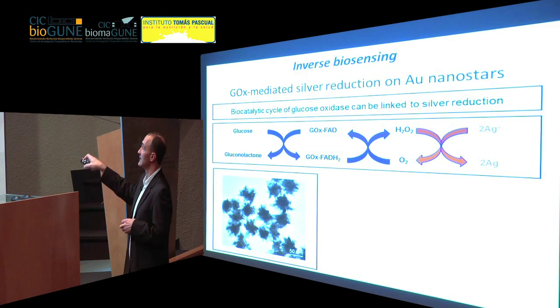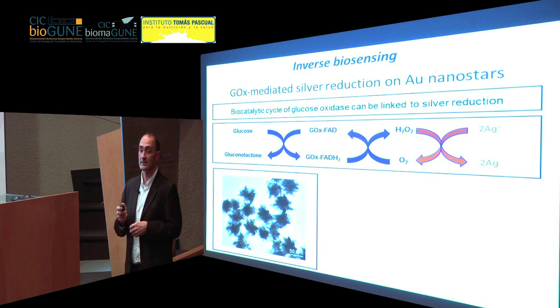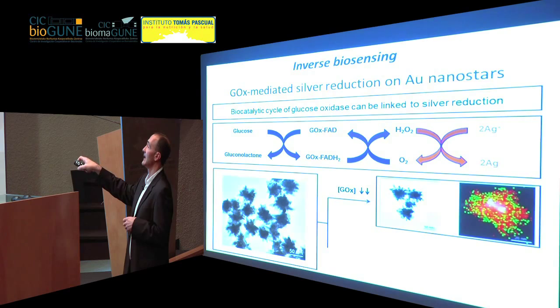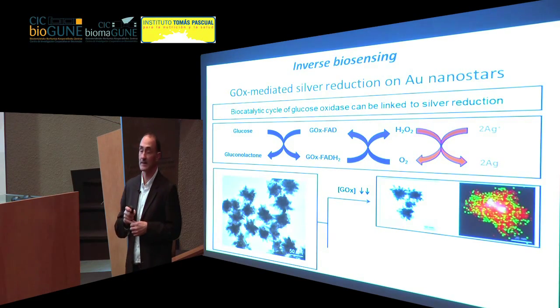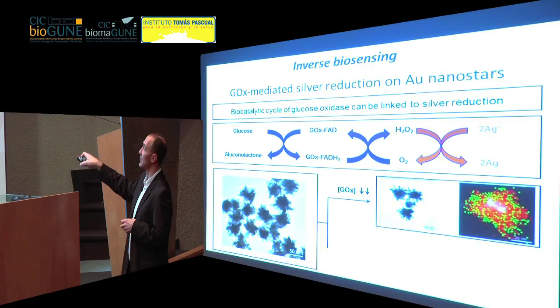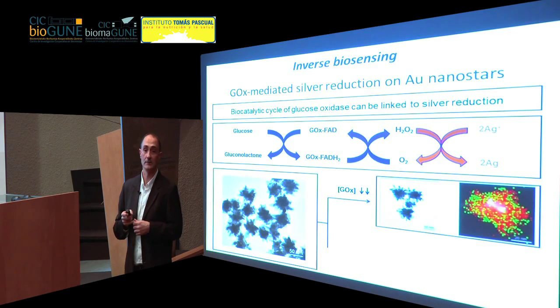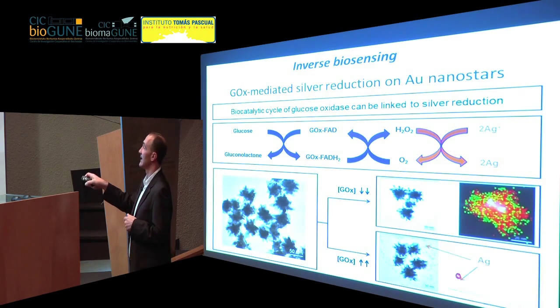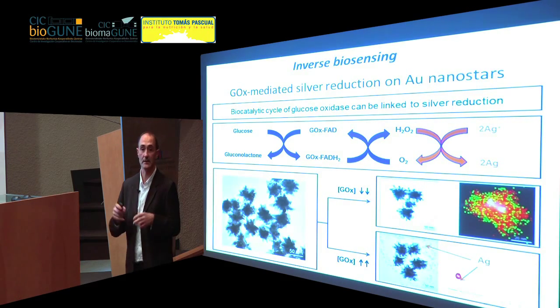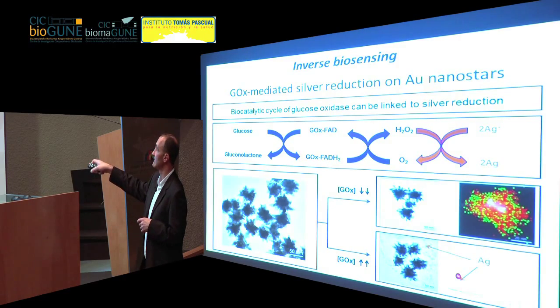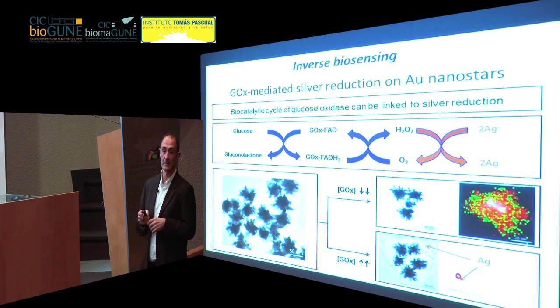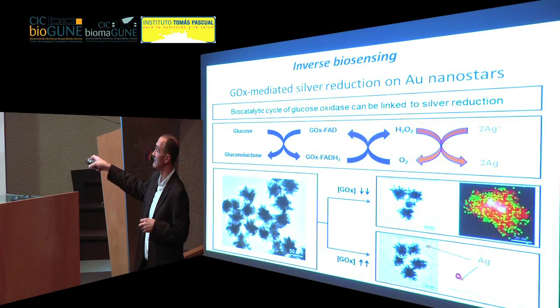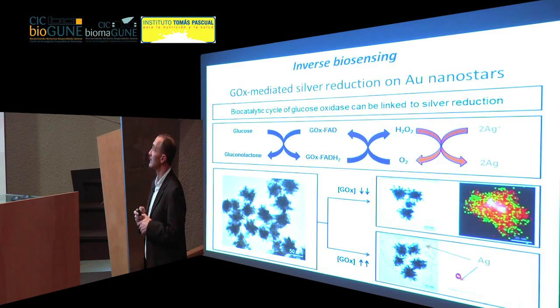So if we do this reaction in the presence of our gold nanostars, we actually find that at very low concentrations of the glucose oxidase, we get a conformal coating of silver on the gold stars. If we do it at a higher concentration, we also get the formation of tiny silver particles in the solution. So most of the silver here is employed in forming these tiny particles, while here most of the silver is going onto the surface.